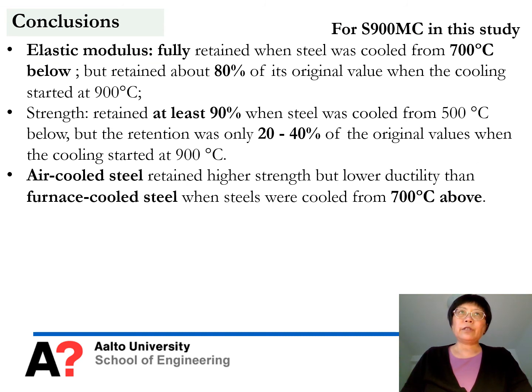So basically the conclusion from this study is that for S900MC, the elastic modulus can be fully retained when the steel is cooled from 700 and below. But if the cooling temperature is 900, then the steel retained about 80% of its original value. For the strength, when the cooling starts below 500 degrees, the retained strength is at least 90%, but after that the strength retention is only 20 to 40%.